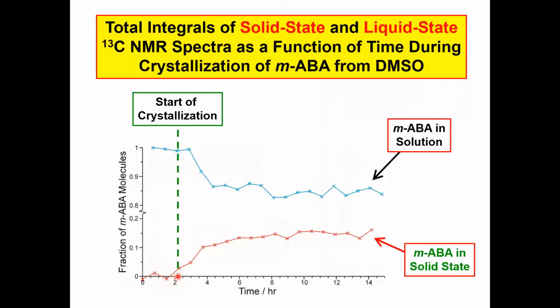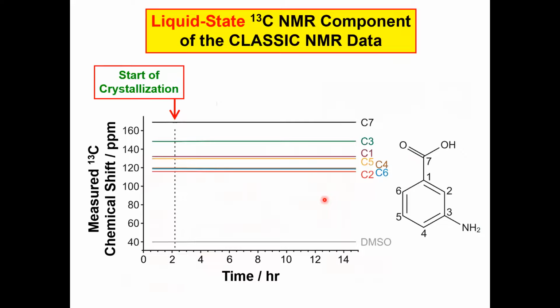And then after 2 hours, we see the increase in the amount of the solid mirrored by a decrease in the amount of the meta-aminobenzoic acid in the solution phase. But much more informative in terms of the liquid phase is to look in detail at how the chemical shifts in the liquid phase change as a function of time during the crystallization. What we're going to do is zoom in to the change in the chemical shift for all the 7 carbon environments in the molecule, as well as in the DMSO solvent as shown here.